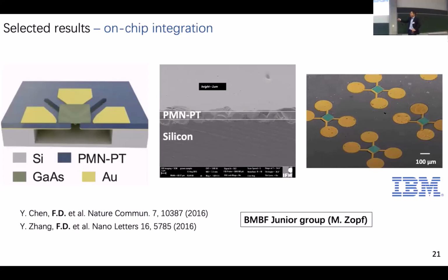The key point is that you don't use a very thick piezo. You use a thinner piezo, and you can achieve exactly the same electric field, because electric field is basically voltage divided by the thickness. That's all. So we fabricate a piezo a few hundred nanometers thick, below 1 micron. We deposit the piezo onto a platform which the industry people like, silicon, and then we fabricate a MEMS structure, undercut it, and then we deposit electrical contact pads.